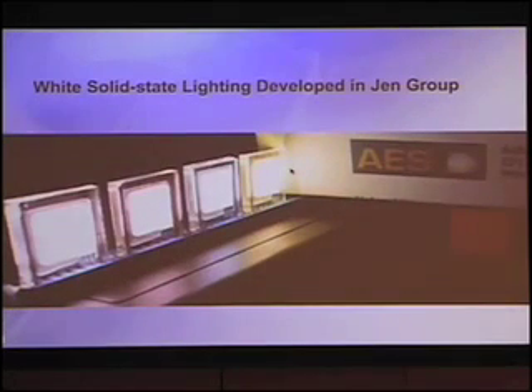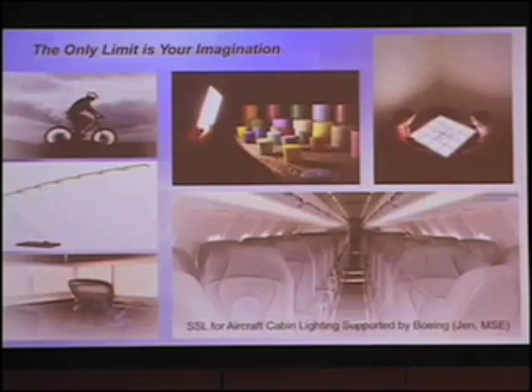LED. So this is about taking an experimental device and trying to scale it up to form very nice white light for solid-state lighting. In one of the Boeing sponsored programs, we are actually developing solid-state lighting for aircraft cabins. So one day, I'm not promising you in the near future, but one day you walk into a 787, the dream airliner, and you find all the fluorescent light tubes disappear. Then you have just a polymer film pasted on top. That is due to this work.